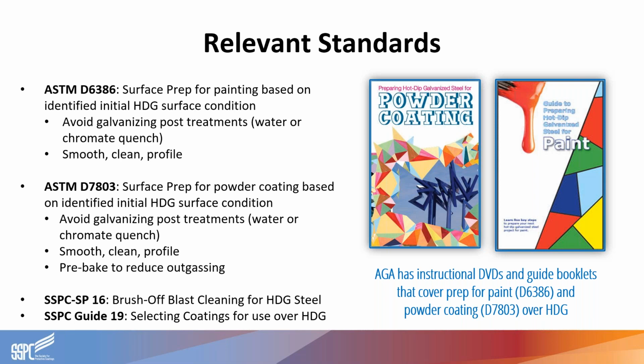If abrasive blast cleaning is desired, but SSPC is not specified, then what can occur is a painter who may be unfamiliar with hot dip galvanizing might use abrasive standards intended for cleaning bare steel, and that can result in peeling or excessive damage to the galvanized coating. So it's important to be aware of that standard as well.